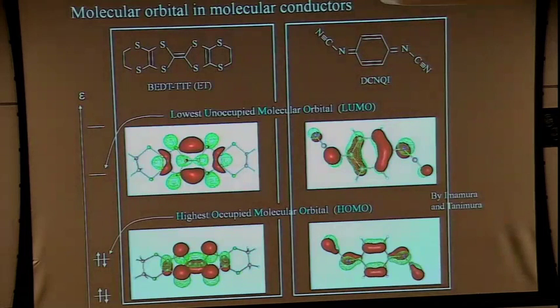In organic materials, the molecule is planar but the symmetry is very low, so the degeneracy is lifted like this. These are the molecular orbitals, with the highest occupied molecular orbital, the HOMO, and the lowest unoccupied one, the LUMO. The level spacing is 1 or 2 electron volts. This kind of molecule has such a profile of HOMO and LUMO.